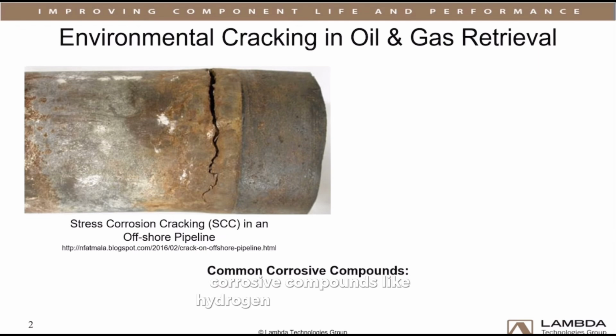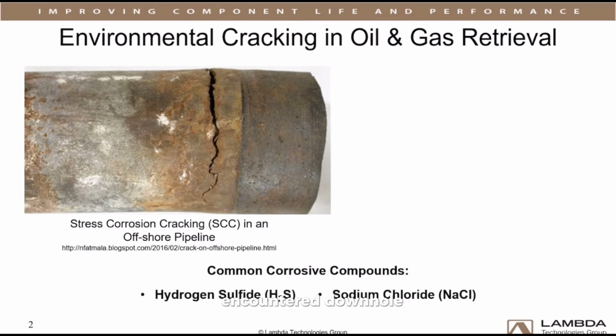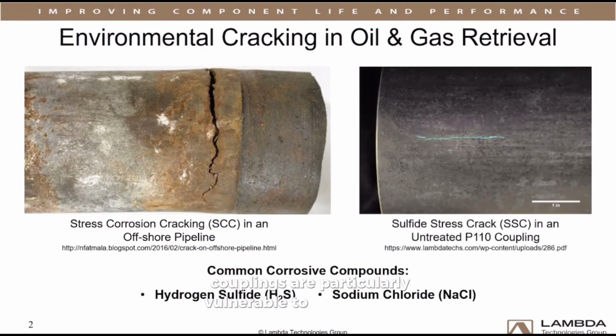Corrosive compounds like hydrogen sulfide and sodium chloride encountered downhole create a sour environment that can cause stress corrosion cracking, or SCC, sulfide stress cracking, and ultimately corrosion fatigue failures in drill pipe and casings. Couplings are particularly vulnerable to sulfide stress cracking due to high stresses imposed in directional drilling. These pictures show detailed views of environmental cracking in pipes and couplings.